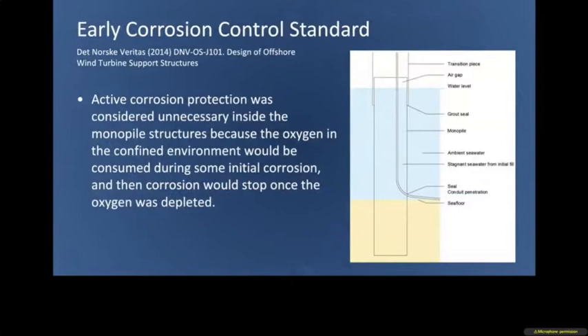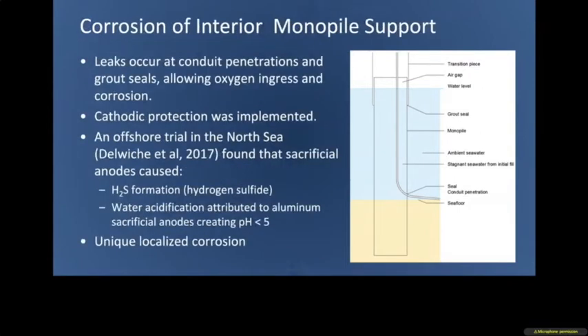So when you place these structures, the early corrosion control standard basically said the interior of the monopile support would not experience corrosion. And that is because if you seal the interior, the oxygen will be consumed. And once the oxygen is consumed, then further corrosion should not occur. However, the challenge of these large structures is actually in creating an airtight seal. And leaks occurred at the conduit penetrations and at the grout seals. And basically that allowed oxygen ingress and corrosion to occur.